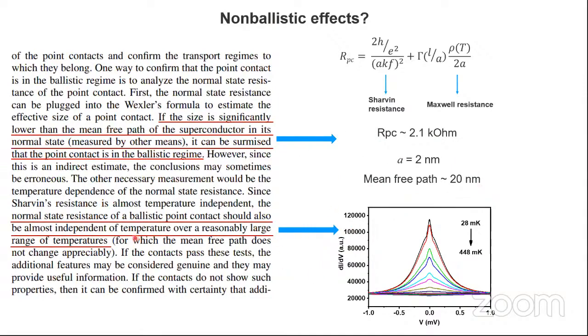And also for a ballistic point contact, the normal state resistance should not change with temperature, because the normal state resistance will be given by these fundamental constants, Planck's constant and the charge of an electron. The bulk resistivity of the material comes into the picture when we have the contact in the diffusive regime. And we found that the normal state resistance does not change significantly.